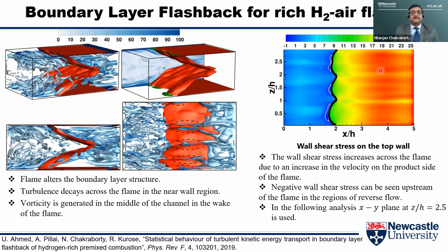This is how the flashback in hydrogen-rich flame in the turbulent boundary layer looks. Once again, these are the Q values. This is the T equal to 1,700 K isosurface. These green zones are the zones where the flow reversal takes place because the flow diverges ahead of the flame, and that sets up an adverse pressure gradient. If we look from the top view, in these white zones, you have negative shear stress.